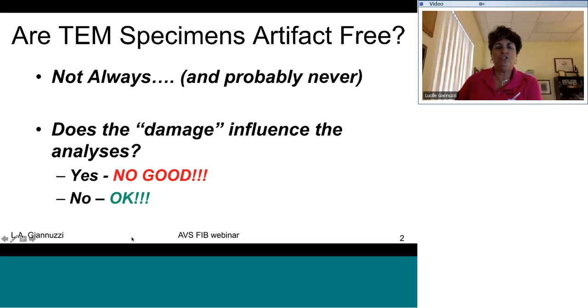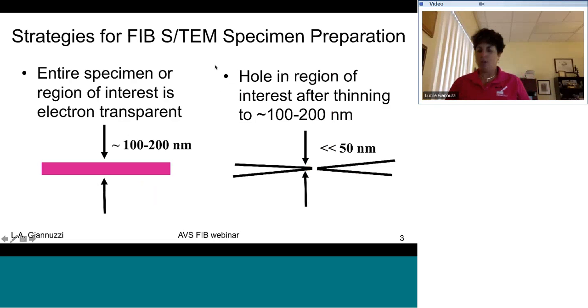The question we should ask is whether the sample is artifact-free, but the sub-question we should ask ourselves is, does the artifact affect the analysis? If the answer is no, then we're good to go. So the strategy for FIB S/TEM specimen preparation is really to start from our 2D sample prep and mill the other side of the sample such that we're left with a sample about 100 to 200 nanometers thick. The other strategy is to start with this and continue to make it thinner such that we just cut through the sample, so that we're looking at very, very thin material. While we're doing that, we clean it up using lower and lower energy ions, which I'll talk to you about later.